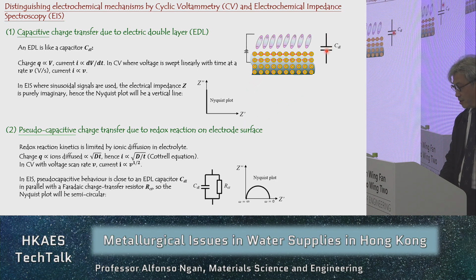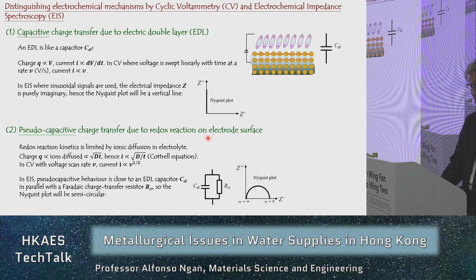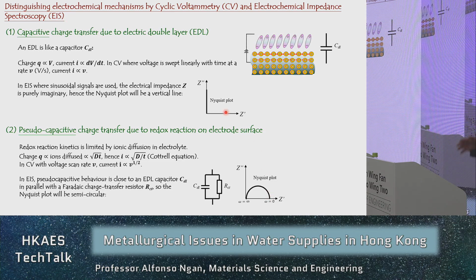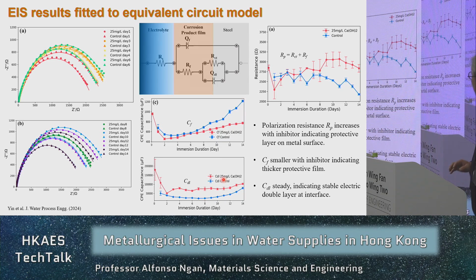For a pure capacitor, we know that the impedance is purely imaginary. So in the Nyquist plot, it will be a vertical line. But in the case of putting a capacitor and a resistor in parallel, that plot will be a semicircle. So just by looking at the electrical impedance plot, we can basically understand whether it is EDL or whether it is pseudo-capacitive charge transfer, which is the redox. So that was the theory.